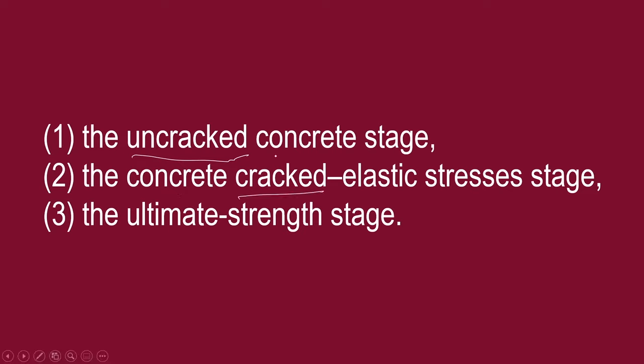This is according to the code, it's right here. I will simplify. According to the code, the modulus of rupture is denoted by f sub r. To compute for the modulus of rupture, this is the formula we have here: 0.62 lambda times the square root of fc prime. fc prime is the compressive strength of the concrete. Usually in the board exam, this fc prime is given. This one is from the NSCP, National Structural Code of the Philippines